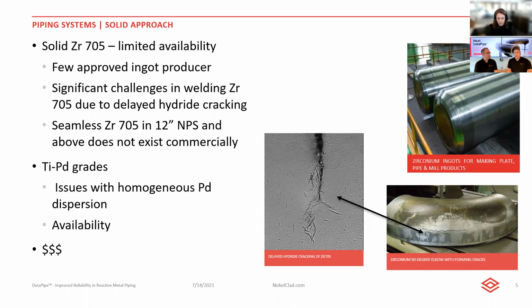Right. In pipe design, you'd like to have everything available as seamless because you get the full credit for the strength of the material without a weld. But in a lot of the alloys, seamless options aren't available above 12 inches, for example. And at the end, you're still paying a lot of money for some of these materials to be used in that service. Exactly. So like you said, zirconium has issues with potential hydriding in the manufacturing. Titanium, for example, has problems with homogeneous distribution of the alloy elements. Correct. Which again, if you're making a thick pipe, then that could be a problem.